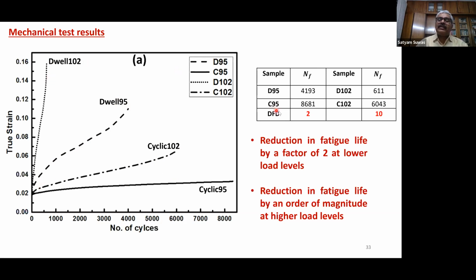And then we cycled it, and we could see that the number of cycles to failure, NF, for 95% dwell is 4,193, while for normal fatigue it is almost double. So the dwell fatigue debit is 2 here. For higher loading stresses, the difference is quite substantial and it becomes 10 times. So that means the damage accumulation is higher if the loading stresses are higher, but again it is much more in the dwell condition than the normal fatigue condition. So this is a very, very interesting thing.